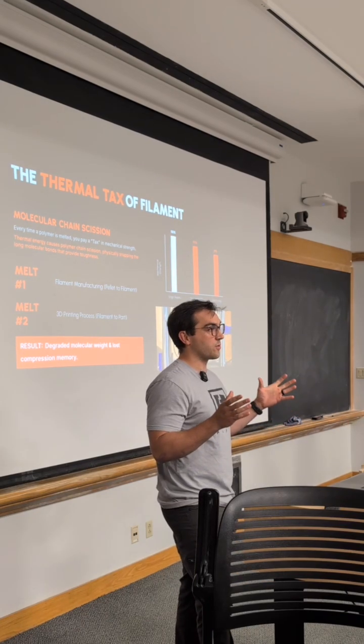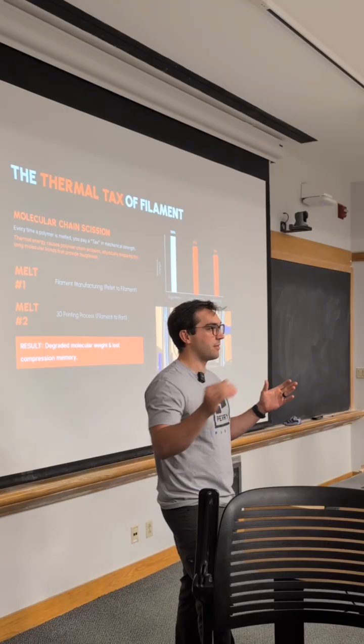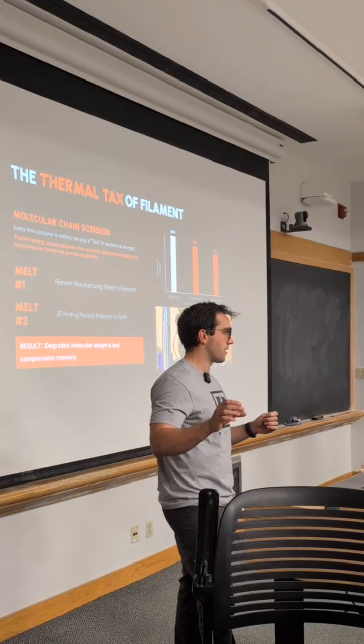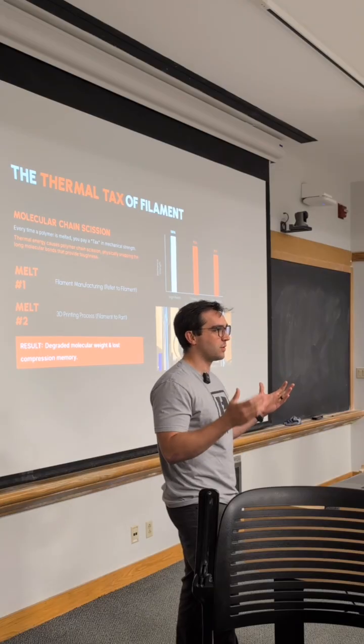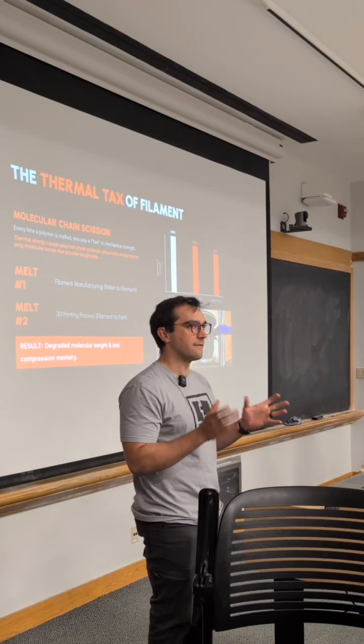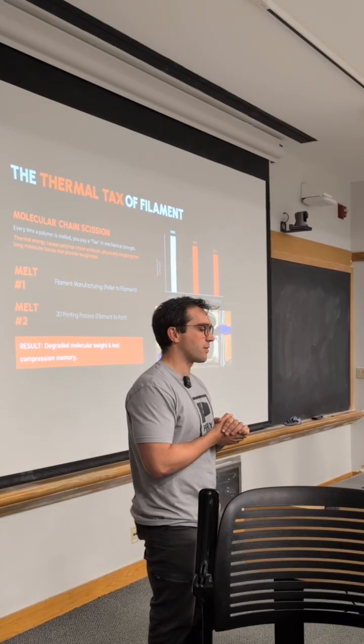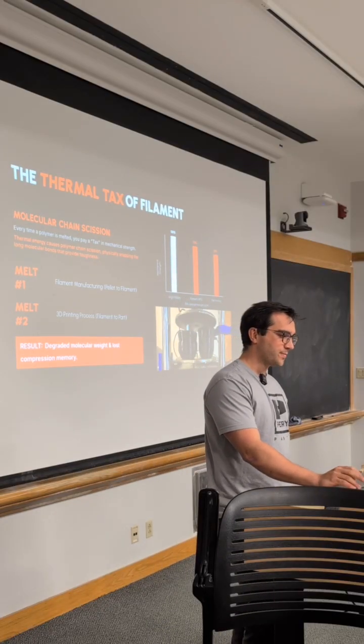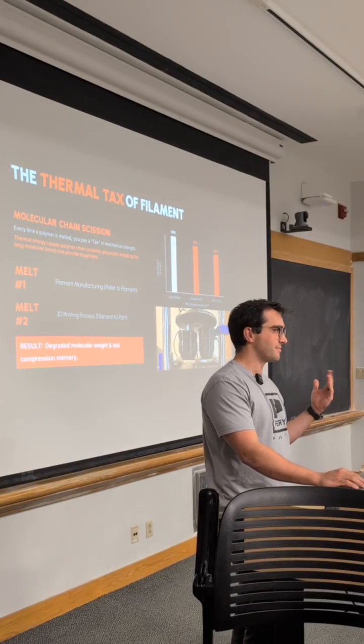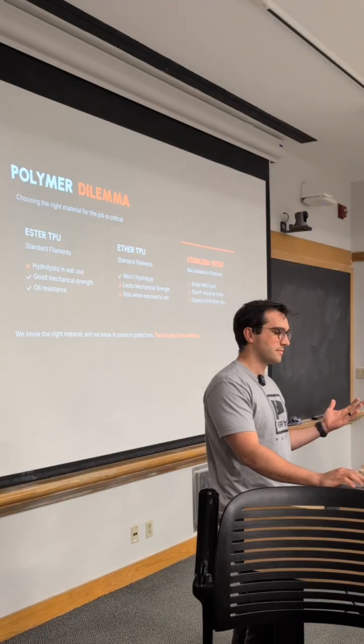This degradation also stacks. So with every subsequent melt cycle, you're compounding that loss. And it's between 5 and 20%, probably closer to 10 to 15 for normal use cases. So fundamentally, filament is flawed in that regard.